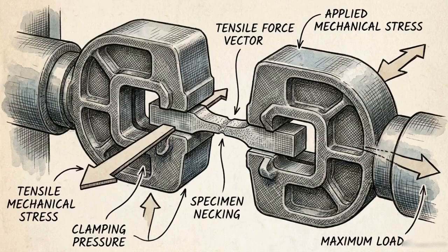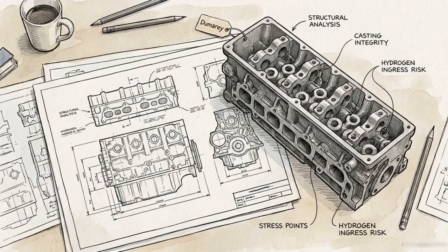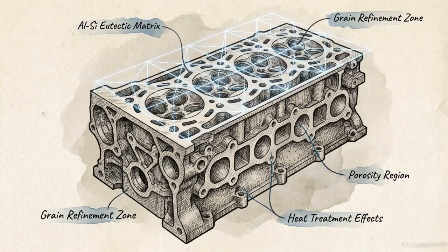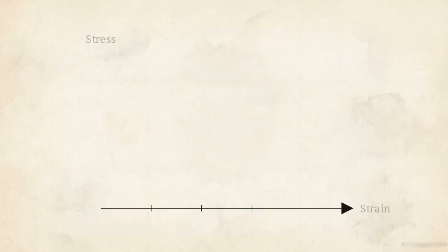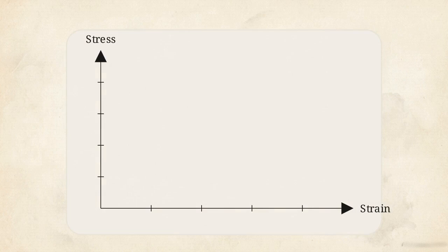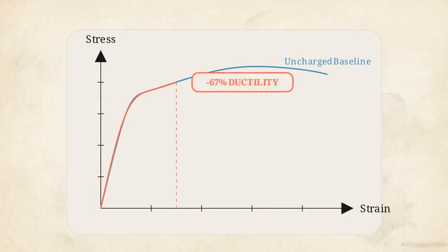We can see this exact mechanism play out in laboratory testing. Researchers at the Politecnico di Torino conducted slow strain rate tensile testing on actual hydrogen engine components sourced from Dumarey. The first component tested was the engine head, cast from an aluminum-silicon alloy. This chart shows the stress-strain curve for that material. When compared to an uncharged baseline, the hydrogen-charged aluminum specimen suffered a massive 67% reduction in ductility.